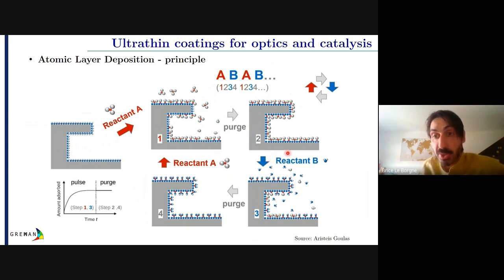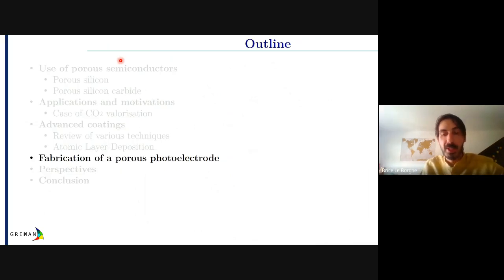Then you pulse a second reactant that will form a new material, a single layer of the new material, with the reaction with the first reactant, and then you purge and you obtain this first atomic layer. You can do as many cycles as you want to form atomic layer by atomic layer deposition, right? So now I'm presenting what we are doing